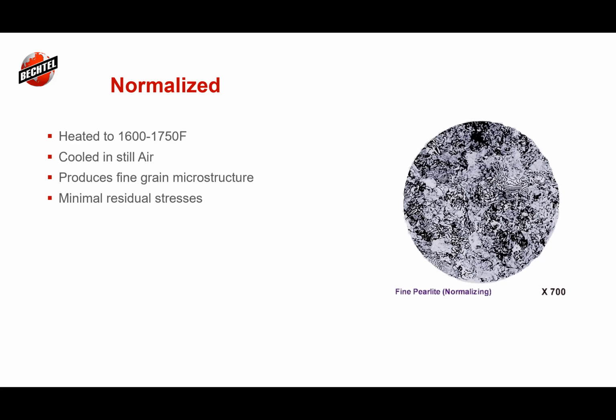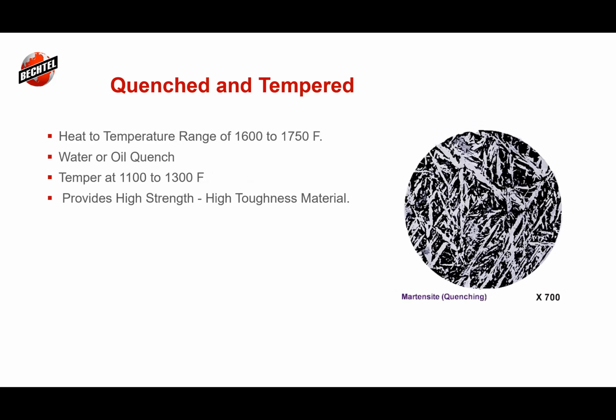And that allows the atoms to move around and become a little bit more stable than we have in the as-rolled condition. And that's different. The quenched and tempered also takes it up to the normalized, but then it cools it down really quickly. Then it brings it back up to a temper, just a little bit below the austenite range. And that allows the coarse martensite to be a tempered martensite.